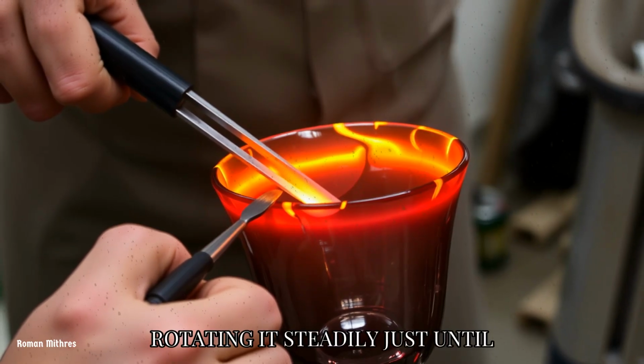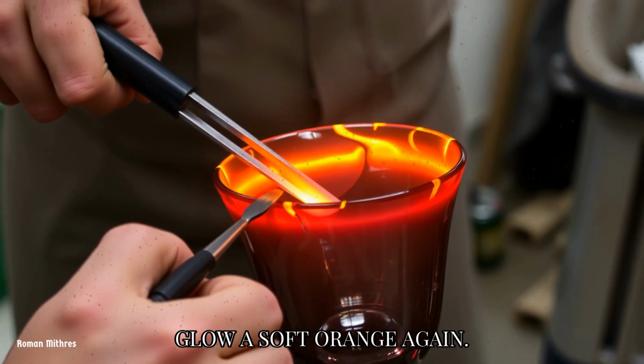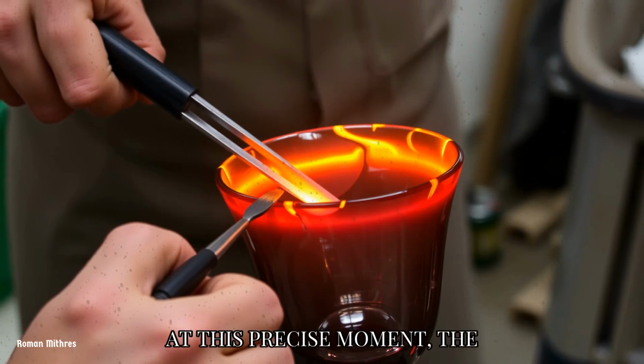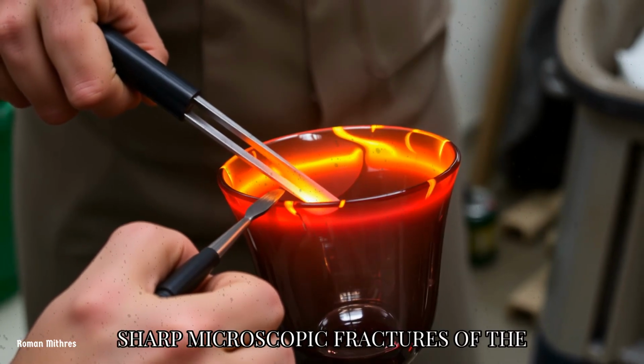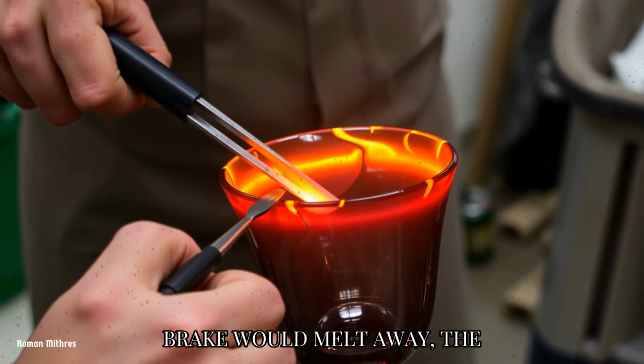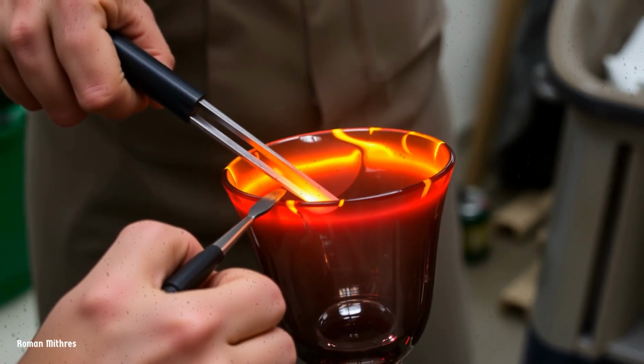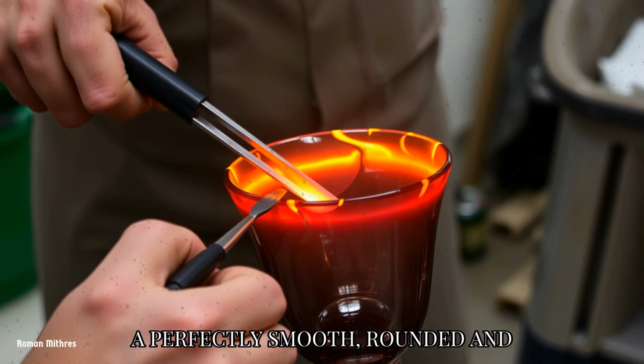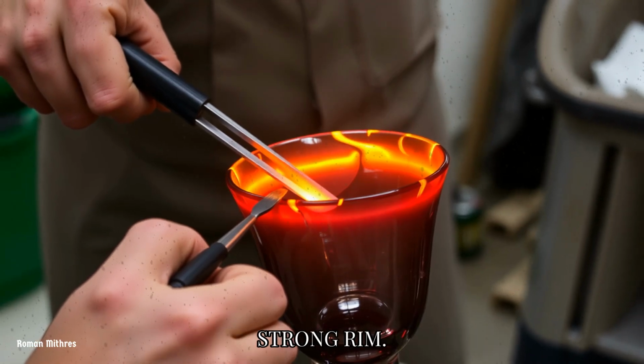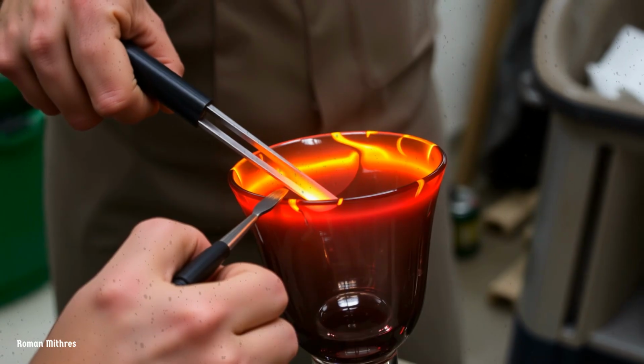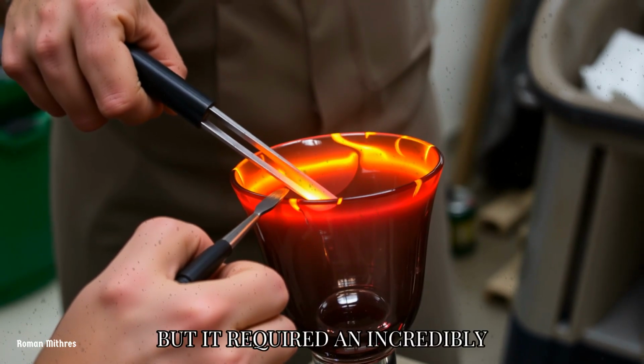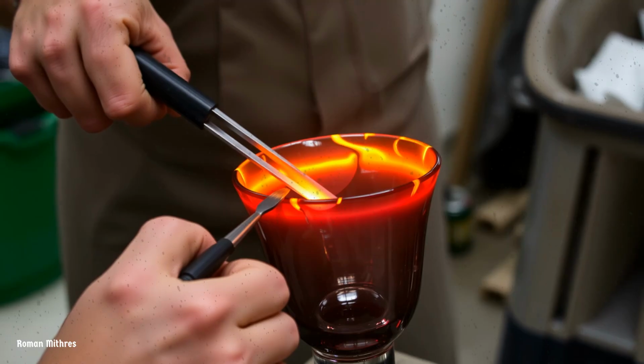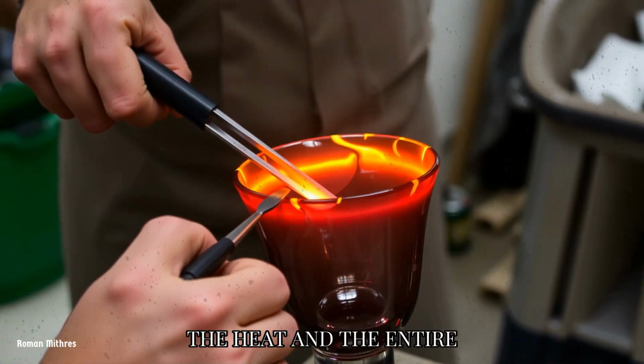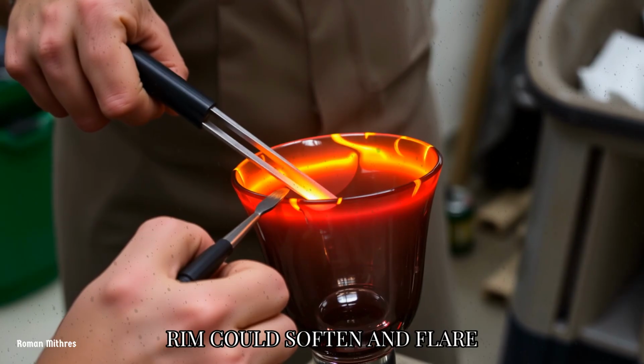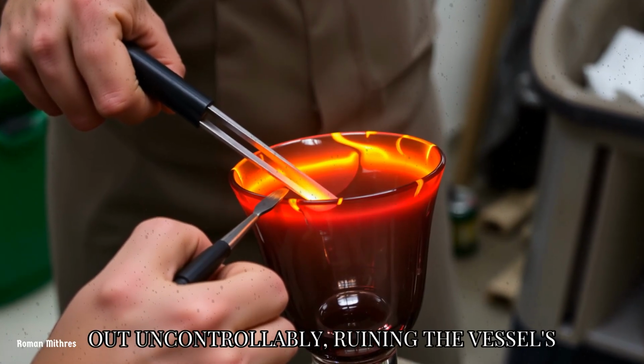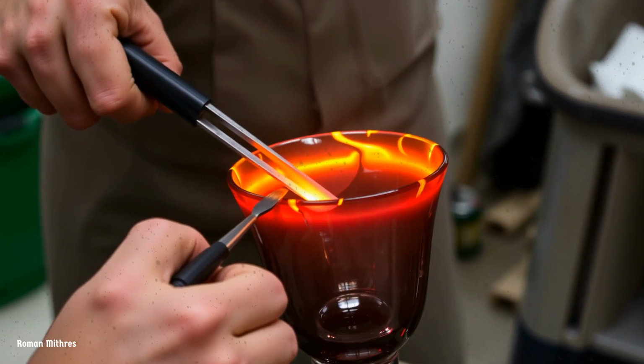rotating it steadily just until the very edge began to glow a soft orange again. At this precise moment, the sharp, microscopic fractures of the break would melt away, the surface tension of the liquid glass pulling the edge into a perfectly smooth, rounded and strong rim. It was a process of healing the glass with fire, but it required an incredibly delicate touch. A moment too long in the heat, and the entire rim could soften and flare out uncontrollably, ruining the vessel's intended shape.